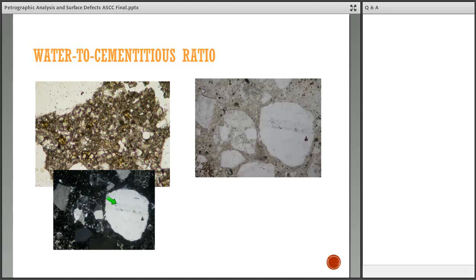And then if you're still not convinced what it is, you can do a water drop test. If it soaks in right away, then you've got a higher water cement ratio. If it takes 2 minutes or 3 minutes to absorb into the paste, then you've got a relatively dense paste, which would be more indicative of lower water cementitious ratio.